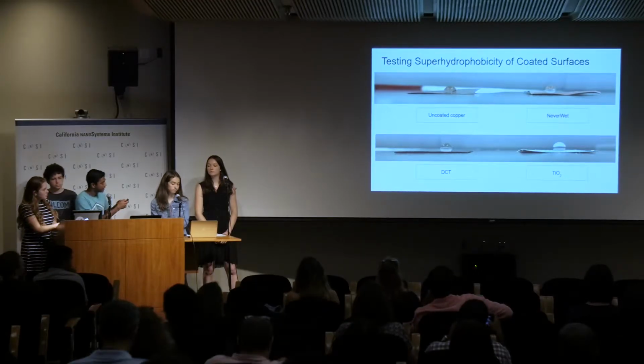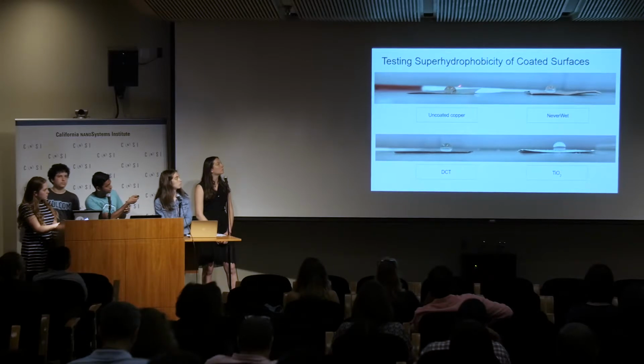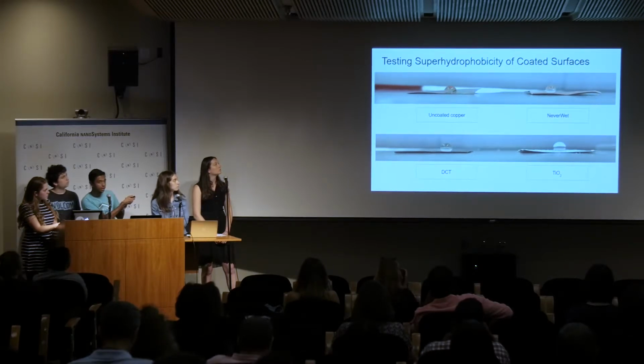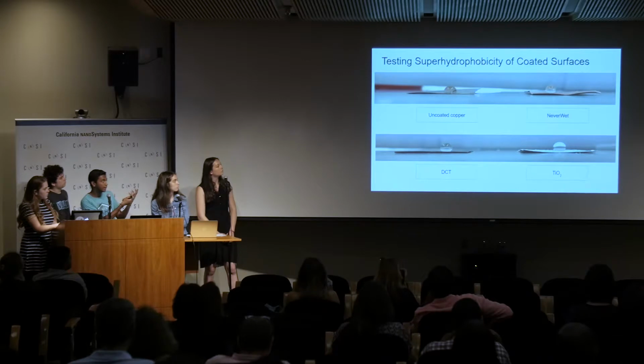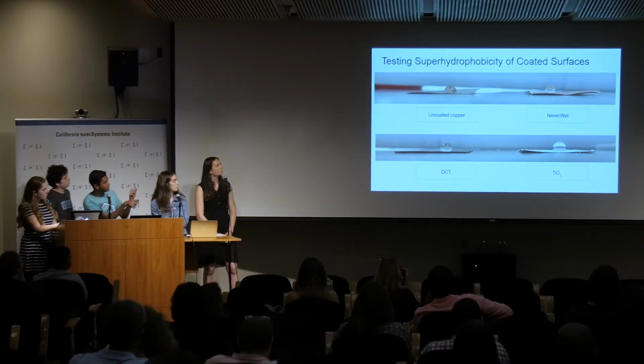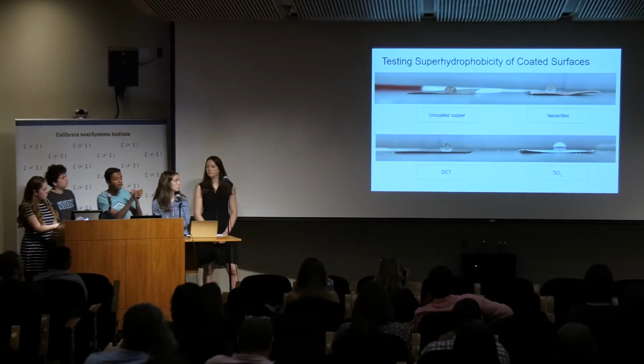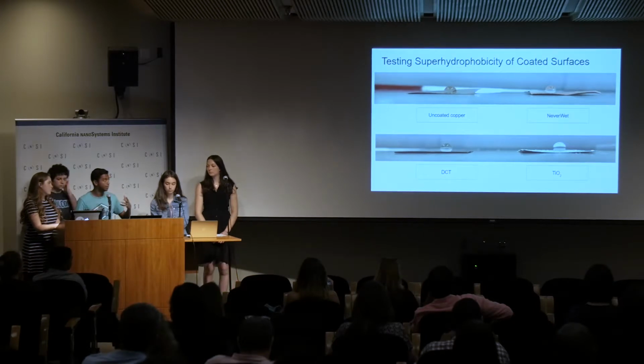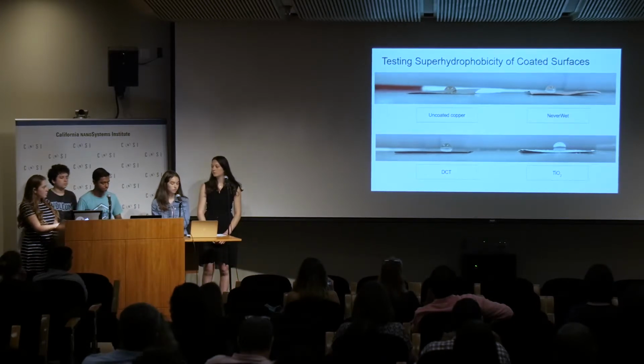Finally, our control for this whole experiment was uncoated copper, as this would provide the best baseline in order to see how good our coatings are, and as we can see how much corrosion occurs before and after submerging it in different pH solutions. As you can see, that is our uncoated copper. It looks kind of smushed because uncoated copper is hydrophilic, whereas you can see the Never Wet, the DCT, and the TiO2 have a lot better beading up because they are superhydrophobic surfaces.